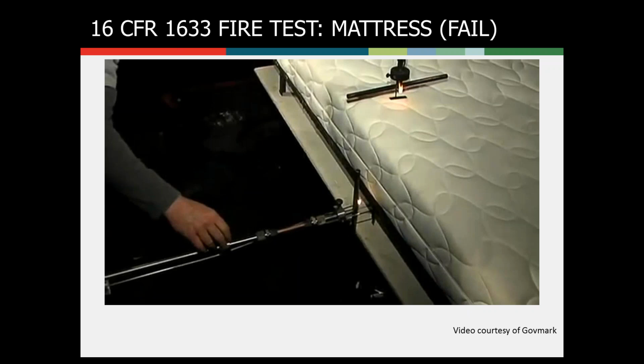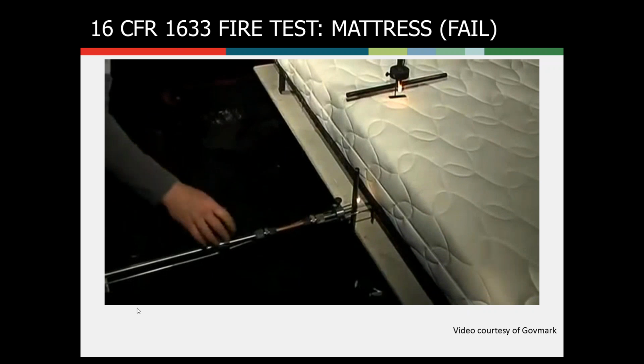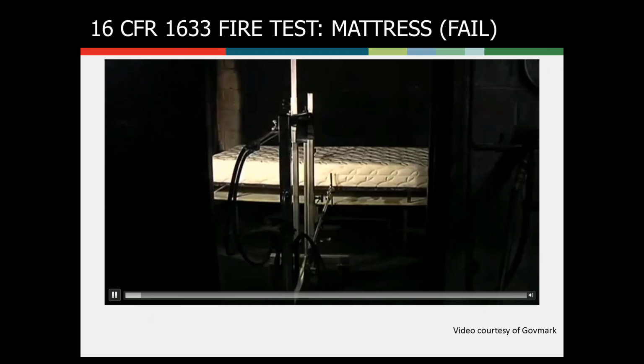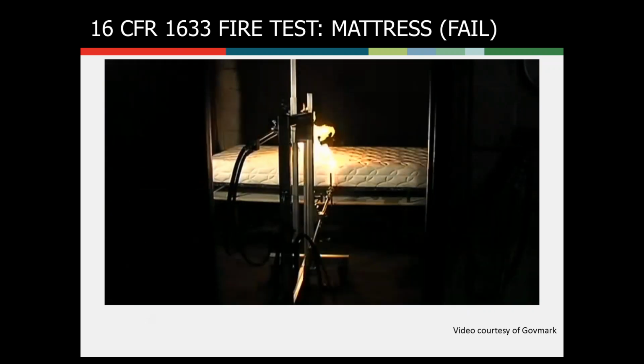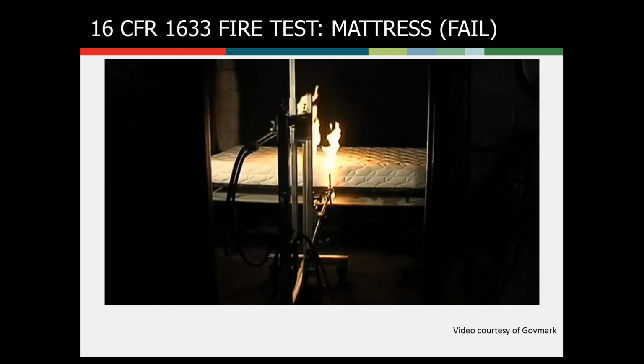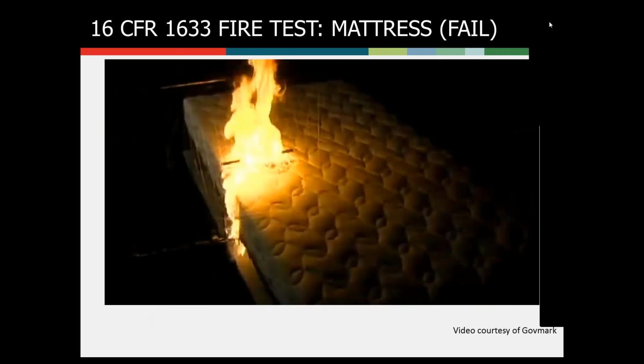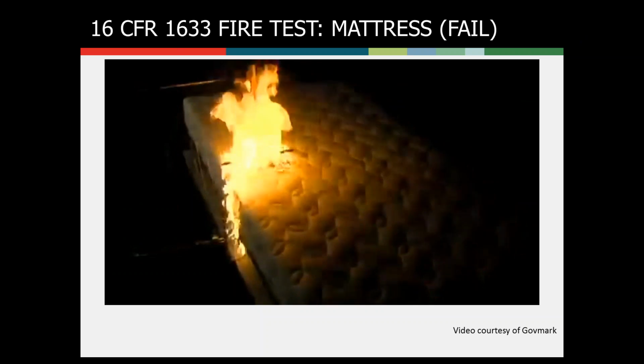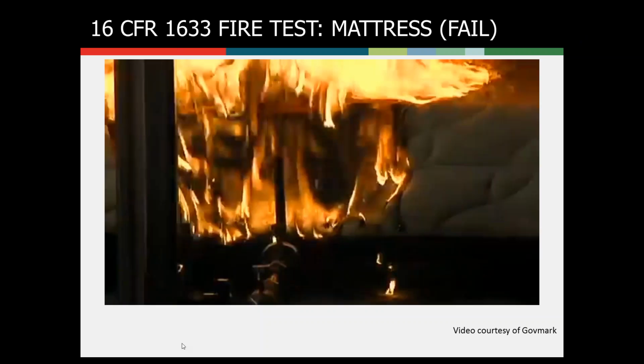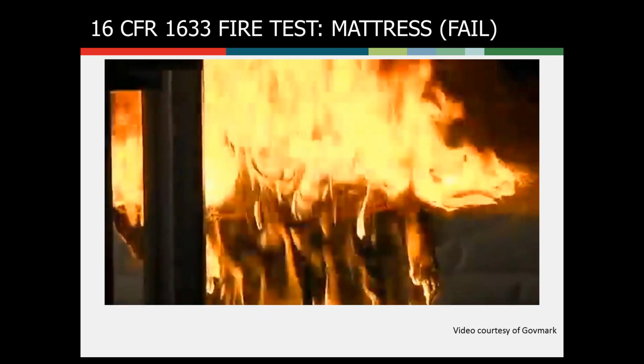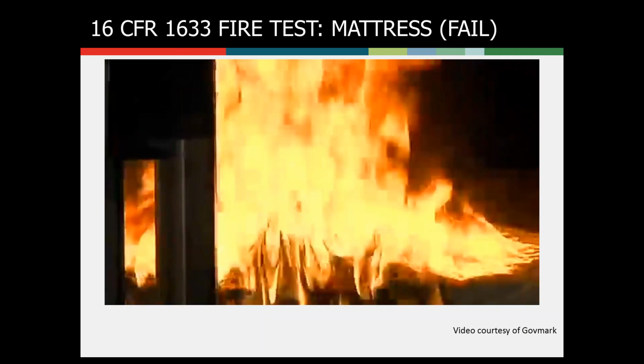Another common test is 16 CFR 1633. It's a test for mattresses. And this is a test whose main goal is to delay the flashover of a mattress when it is ignited in a typical bedroom fire. So it tests full-size mattresses. They have to be at least twin size, up to king size. And so in this case, you're going to see this mattress is not going to pass this test.